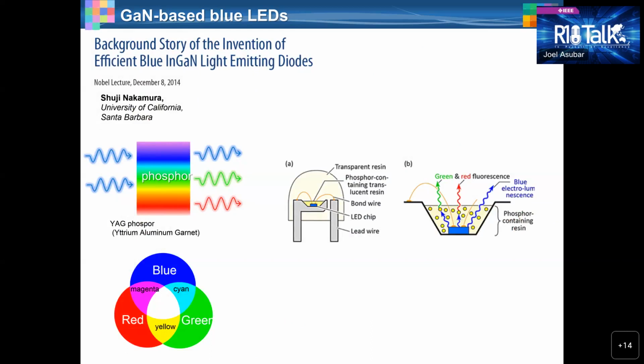Well, another approach, and actually the most successful approach to produce white light, is to combine blue LED with a phosphor. A phosphor is a material that can emit light after its excitation by external energy. For a phosphor, the general rule is that the emitted light should have lower energy than the light used for its excitation. Because blue light has high corresponding energy, different lower energy colors ranging from green to red can be generated using phosphor.